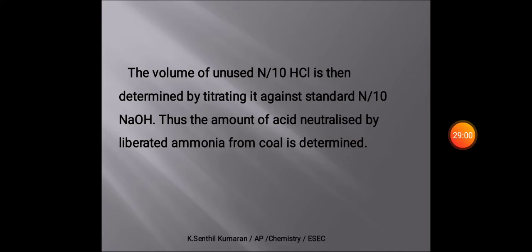How much unused HCl is present in the burette? Using this we find out how much ammonia is formed in the reaction. Then the calculation of the percentage of the nitrogen content is equal to the volume of unused HCl divided by initial weight of the coal sample into atomic weight of the nitrogen, that is 14, into normality of the HCl into 100. So using this formula we find out the percentage of nitrogen content in the coal sample.